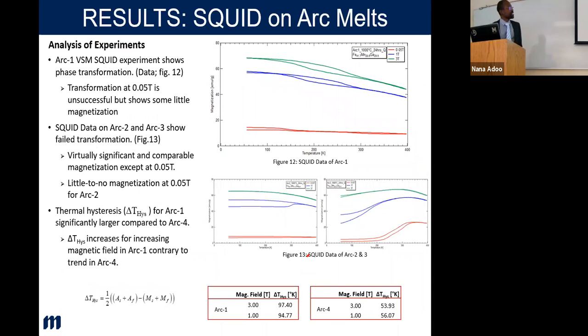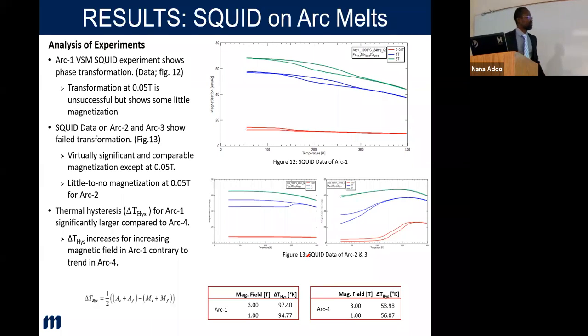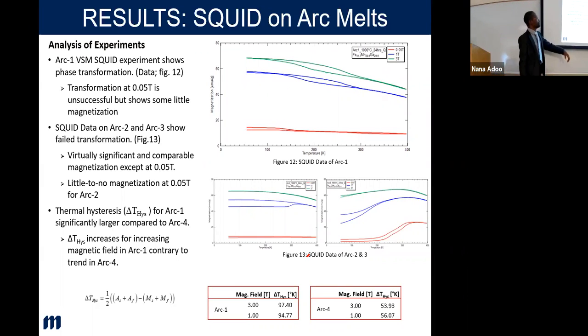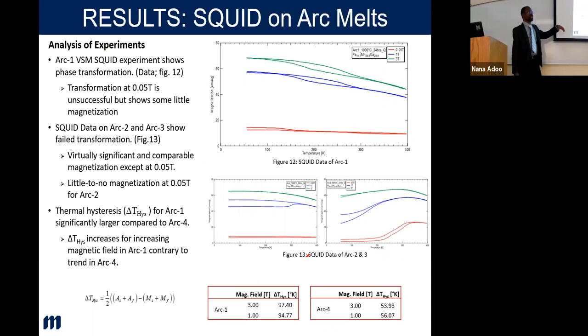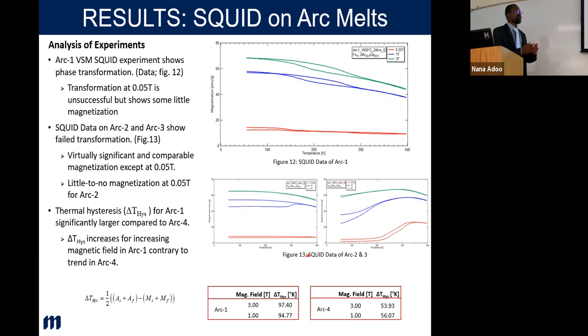I failed in some of them. Two of the arc melts actually succeeded, and then 2 failed. And these are the failed tests in the bottom. So even though they magnetize, they do not show this shape memory or transformation effect. It doesn't mean they couldn't be used for other applications, but for the purpose that we want, it won't work. So then I also measured those hysteresis, and you could see some of them produce very large hysteresis, and then others also very low, but they all failed.